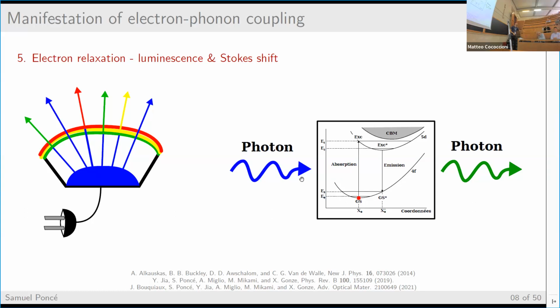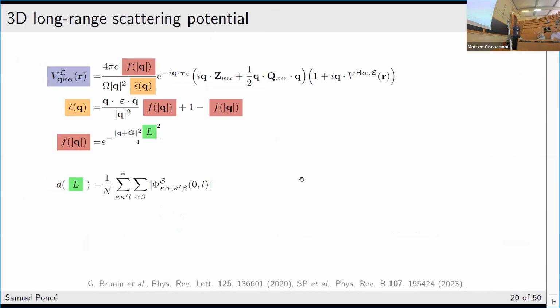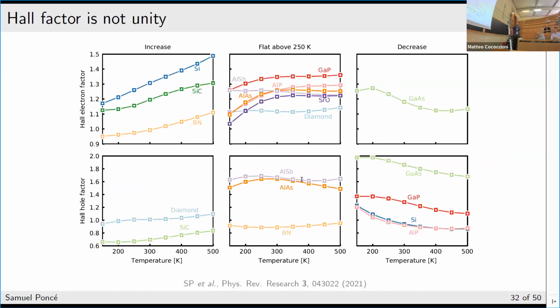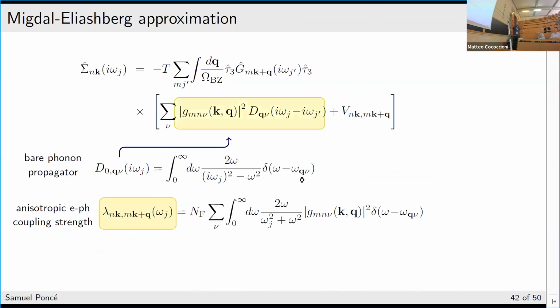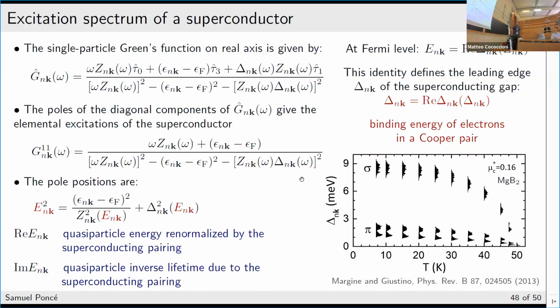Good. Other questions? You showed some results of MgB2. Can you go to the last slides? Yes. So basically, you have a Tc of the... What I was wondering is that MgB2 has 39 Kelvin, and this seems to be overestimated. Yes. But still the mu star is quite high with respect to the typical value. So basically, if you decrease the mu star, you would go lower. Yes, that's correct. So do you have a comment on this overestimation?